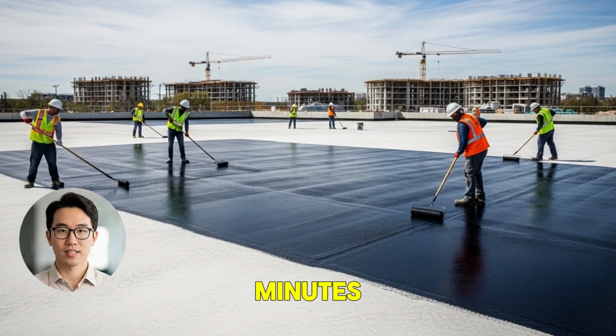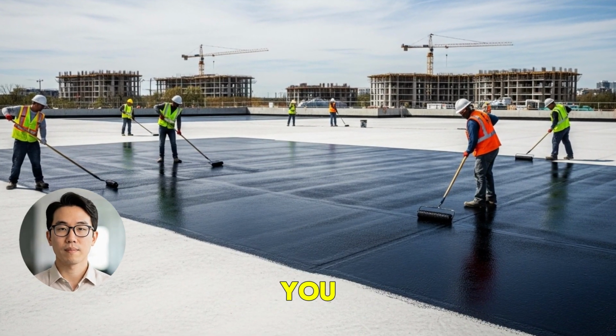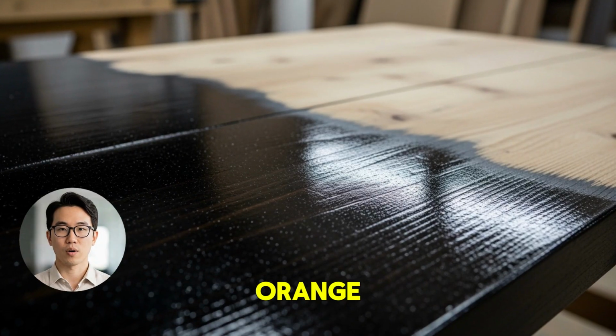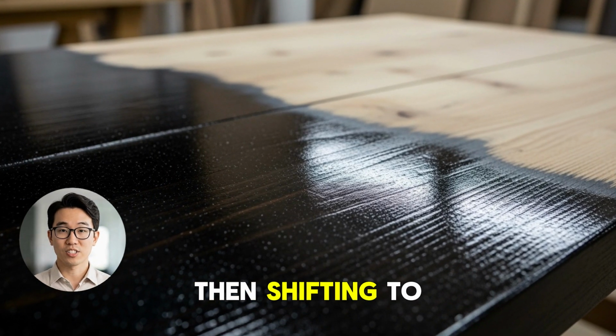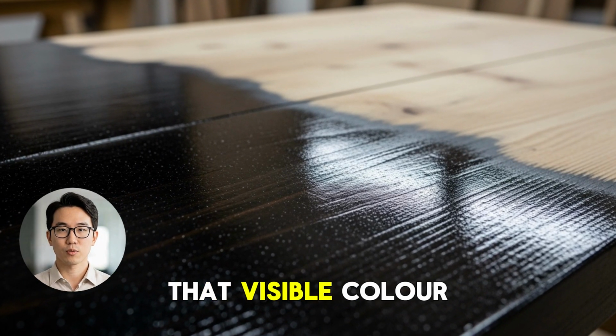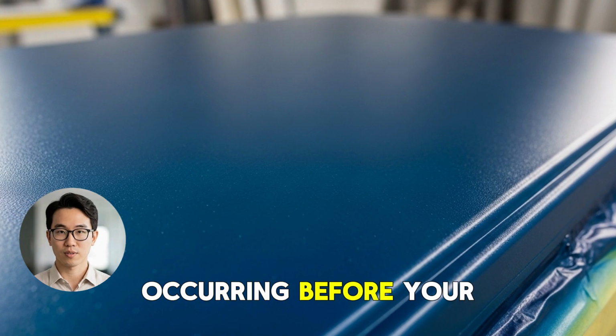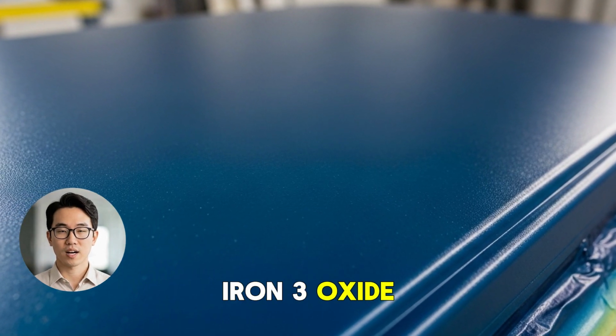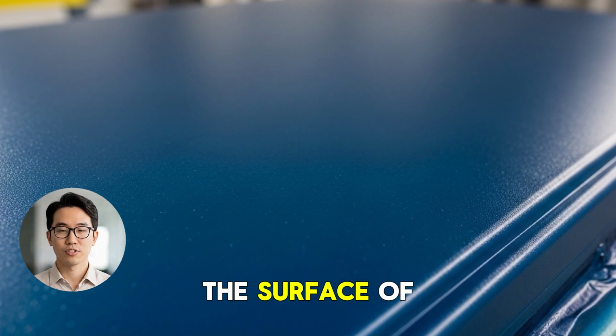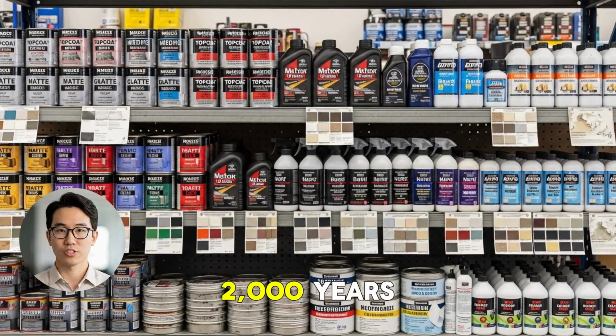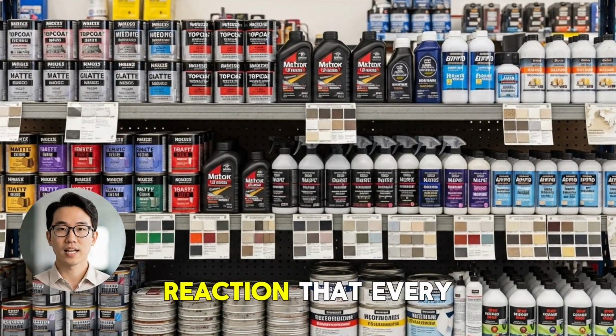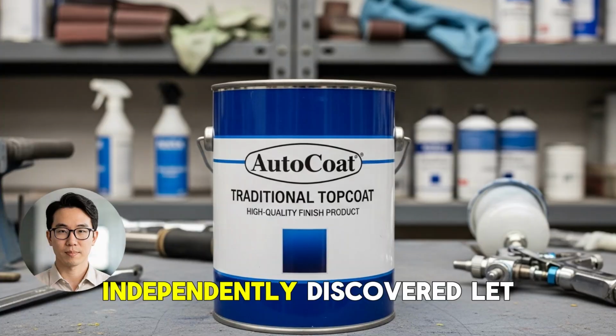Within 10 to 15 minutes, you will see it happening right in front of you. The rust will begin changing color. Orange-brown fading to dark gray, then shifting to a deep blue-black. That visible color change is the molecular conversion occurring before your eyes in real time. Iron 3 oxide is becoming iron 3 tannate on the surface of your metal. You are watching 2,000 years of proven chemistry perform the exact reaction that every civilization with iron independently discovered.